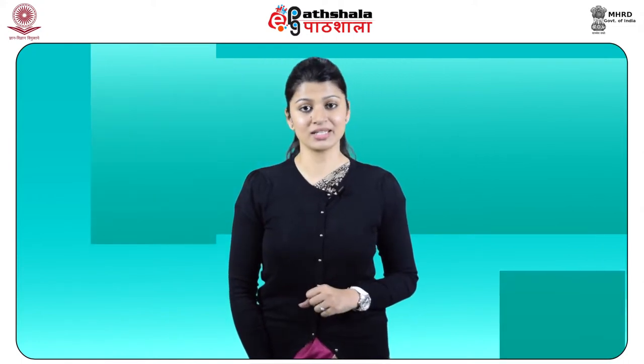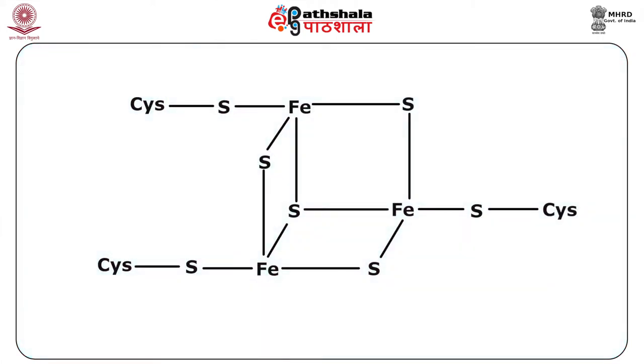However, an error was detected in the analysis of this structure and it was corrected to have a non-planar Fe3S4 geometry. This structure seemed to be derived from the 4 iron, 4 sulfur core by the removal of 1 iron sulfur unit from one of the 8 corners of the cube. This cluster composition was supported from EXAFS data on the Desulfovibrio gigas ferredoxin. 3 sulfide ions bridge 2 iron ions each, while the 4th sulfide bridges 3 iron ions. Their formal oxidation states may vary from Fe3S4+, where all the iron ions are in plus 3 form, to Fe3S4 2-, where all the iron ions are in plus 2 form.